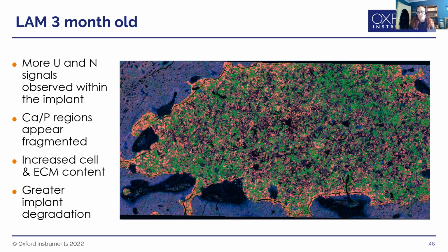It's one of the many projects I've been working on where I've used higher kVs. So with the Ultim Extreme Detector, you can go up to 7 kV, or you can push it slightly higher up to, say, maybe 10 kV. You will get a bit of a background of backscattered electrons hitting it, but it really depends on what you're doing. So these were acquired at the top range of the Ultim Extreme Detector. So we got a lot of signal, but we had the nitrogen signal in there. And that was the key part of the analysis here.